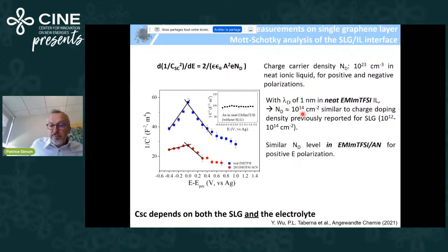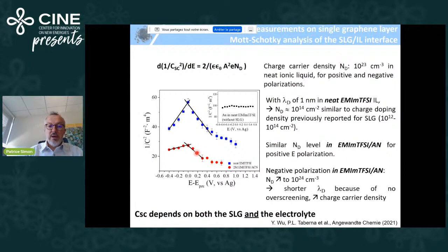So when you move from EMI TFSI to EMI TFSI in acetonitrile, you have more or less the same charge carrier density for positive polarization, the same slope here between the red and the blue for positive. However, for negative polarization, still considering the Mott-Schottky model, you see that you increase the charge carrier density to 10 to the power 24 per cubic centimeter, while it was 10 to the power 23. Just because, in fact, when you add solvent, you decrease the Debye length, because there is no more charge overscreening and no more strong ion correlation between the ionic liquid ions.